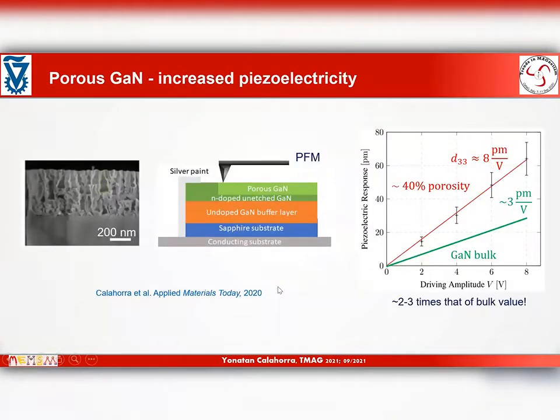So our interest is in porous gallium nitride, this kind of material in cross-section. Recently we observed that porosity in gallium nitride can induce interesting piezoelectric properties. That's another type of multifunctionality, if you want. Using PFM, an AFM apparatus where voltage is applied between the tip and the sample, and the AFM records the piezoelectric deformation, we found that at about 40% porosity, the measured, or effective, d33 piezoelectric coefficient was 2 or 3 times higher than that of bulk.